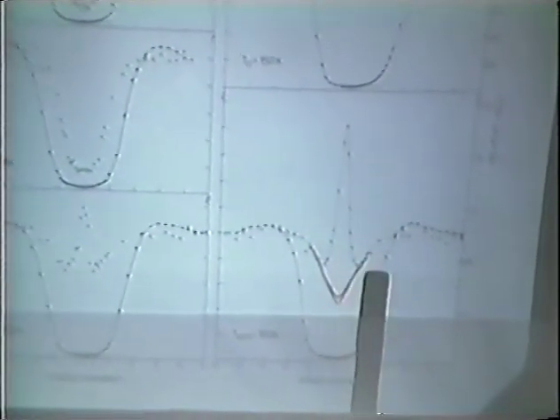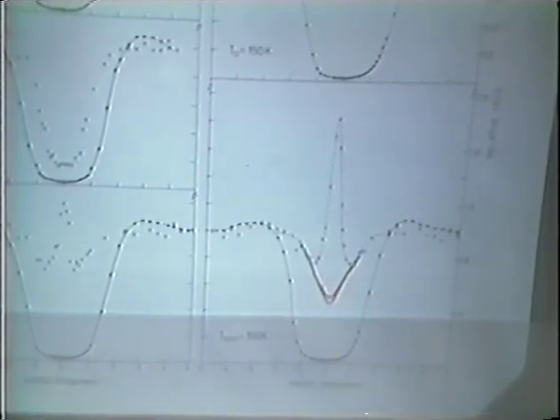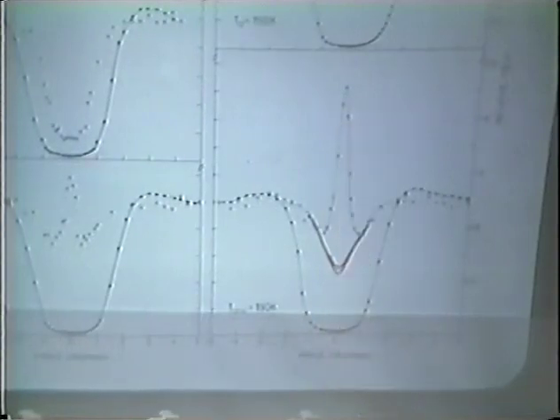We then see a narrow dip, and superimposed on that, we see a flux peak here. That can be analyzed in the way that, for the narrow dip, some part of the hydrogen is sitting in an octahedral site displaced 0.3 angstrom away from the octahedral site towards the vacancy, and some part is sitting at a site close to a tetrahedral site.